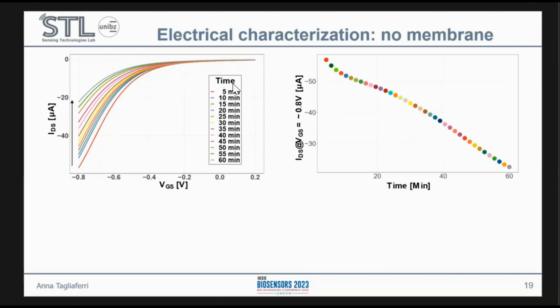To better see this phenomenon, we plotted the on current versus time. That is the highest current that we measured at minus 0.8 volt. This is seen in this plot here on the right. We can see that over time, the current decreases very rapidly in the phenomenon that I was talking about before. We only left our devices running for 1 hour, but it is plausible that if we had left them for longer, the current would have reached zero very quickly after this.